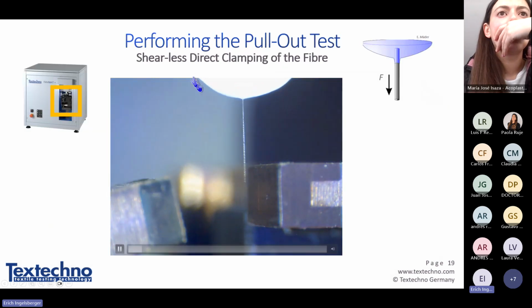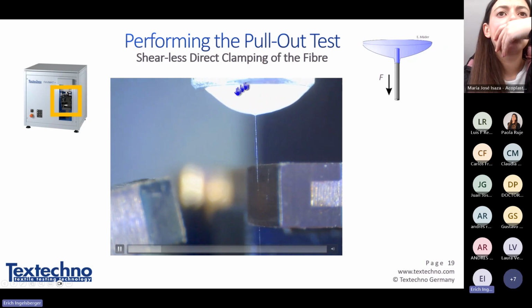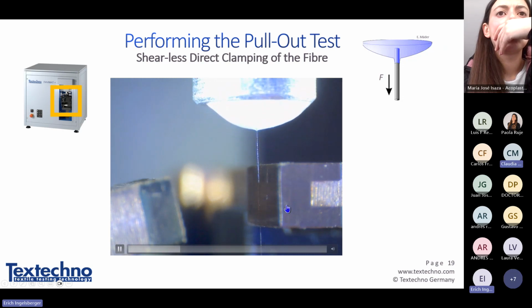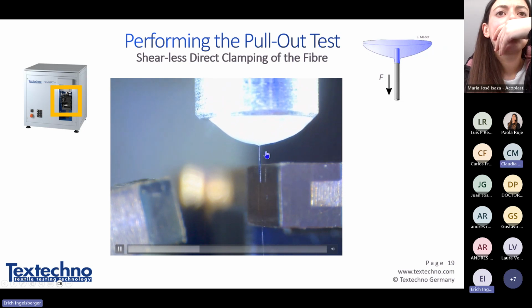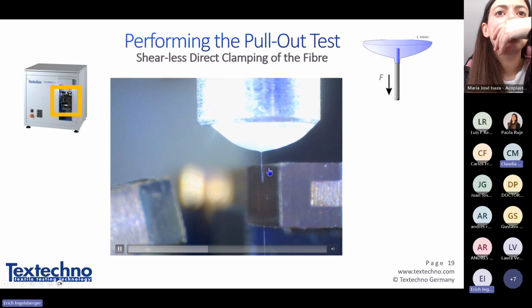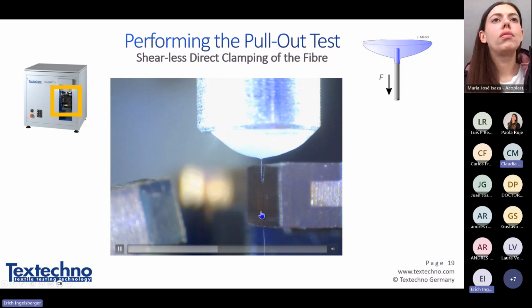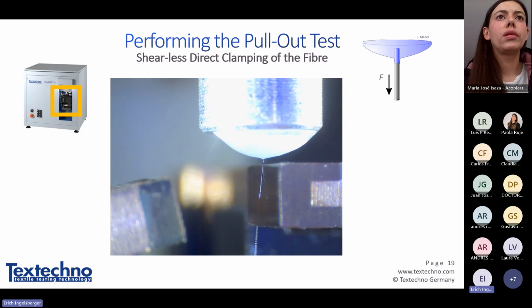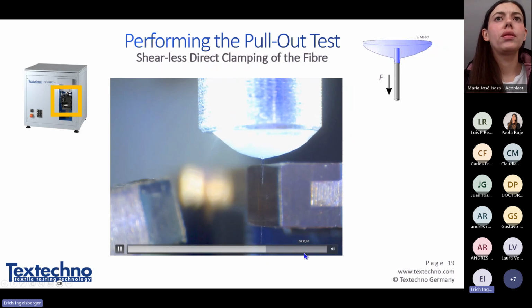Here you see the droplet, the matrix, coming from the top side, moving down, and by mechanical adjustment and looking with a microscopic camera, we adjust the system so that first the fiber touches the clamping area. Here, for example, it moves too much to the right, so it's now not touching.